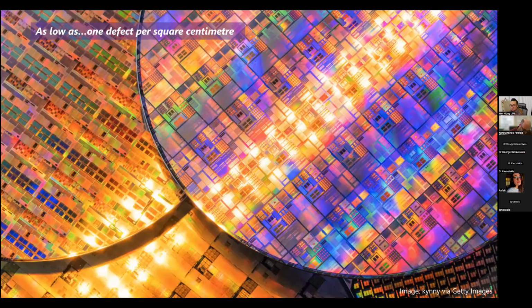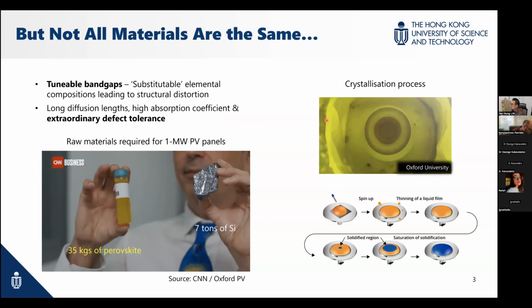Perovskite is a very interesting material, especially compared to the most widely applied material, that is silicon. Silicon perhaps has one defect in a large area like 1 square centimeter, but perovskite is not like that. And we can process it from solution, as many of you know, and people are also working on organics, and know about the different transport mechanisms in this kind of novel material.